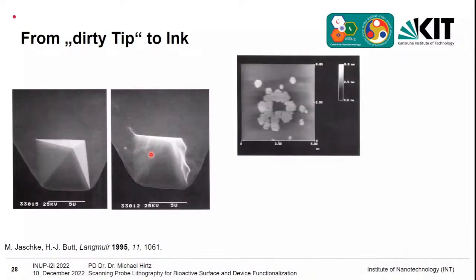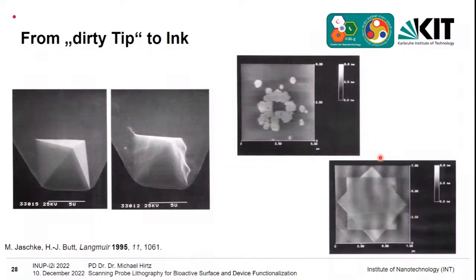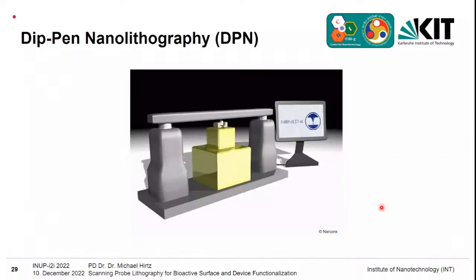And this also leads to observations that if you go with a dirty tip to another place on the gold surface where there was no organic monolayer before, then after scanning it with the tip, you also see growth of self-assembled monolayers there. And then the idea came up, okay, we can also do this on purpose. So we take what was once considered a dirty tip and really on purpose ink it with the thiols. And then if you scan a surface, you can see you can orderly transfer these kinds of monolayers. And this led then to the advent of the so-called dip pen nanolithography.